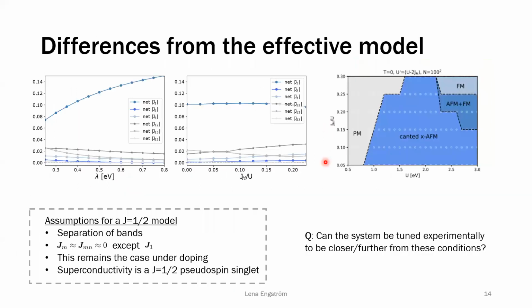To see more specifically, I can show some results here. We don't have an exact value for U and JH, the Hund's coupling here. We just have some interval that fits with experiments for this model. We know that we should be getting this antiferromagnet, so this is at zero doping, just looking for this antiferromagnetic order. We still can have quite a few values of the Hund's coupling that are valid.